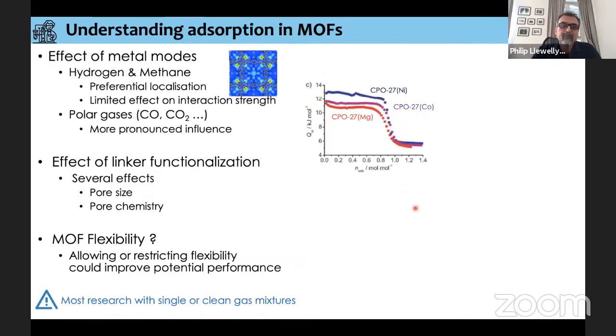So here we go. Before we take a break, I just want to make a first series of conclusions. If we try to understand adsorption in MOFs and make some very first generalizations, the effect of metal nodes on hydrogen and methane gives us an idea that these are maybe areas of preferential localization, but with maybe limited effect on the interaction strength. This is again the result we saw earlier on the CPO27 material for hydrogen, and the differences in energies are only around 2 to 3 kilojoules per mole, which isn't huge.